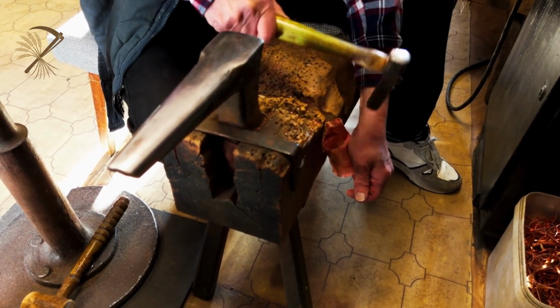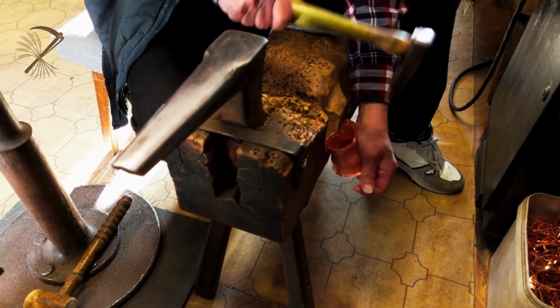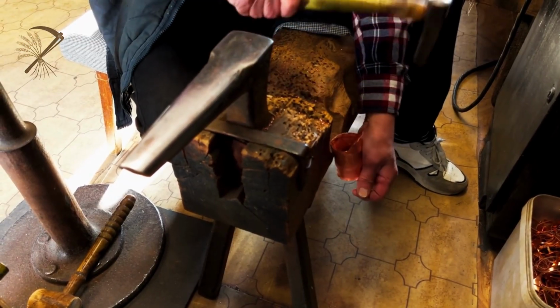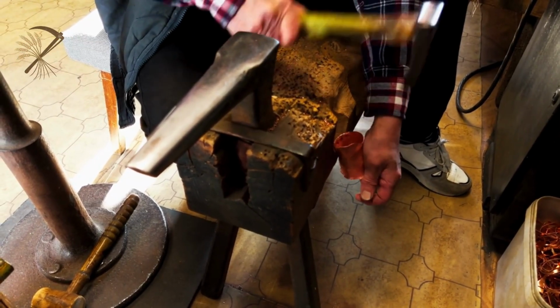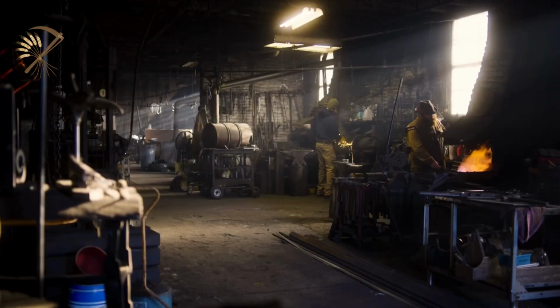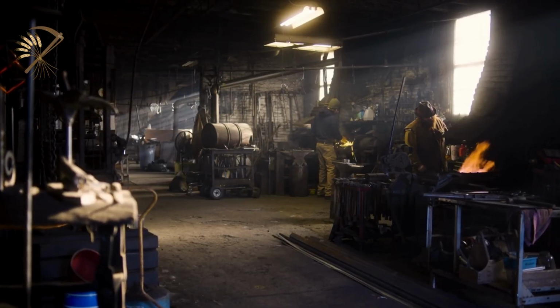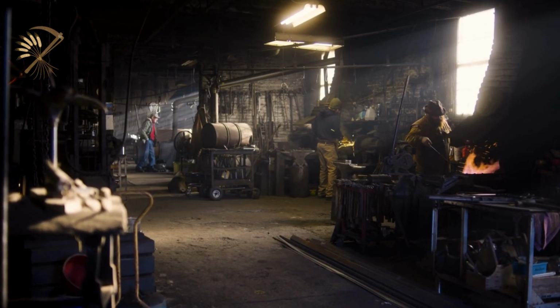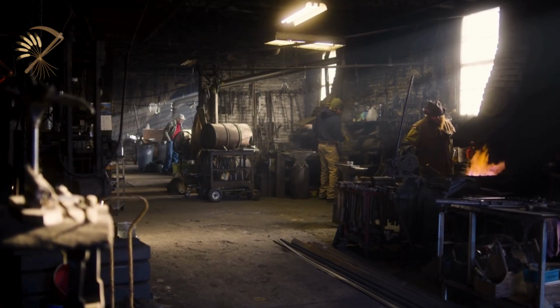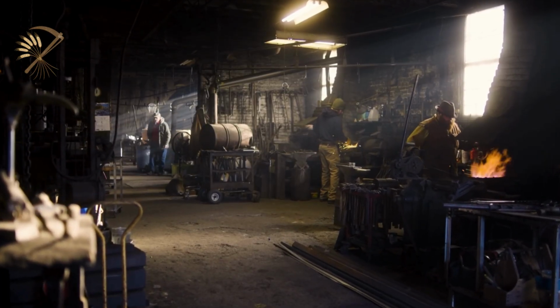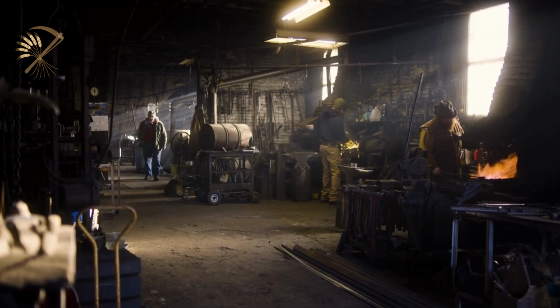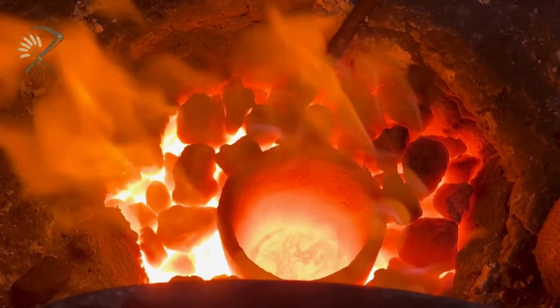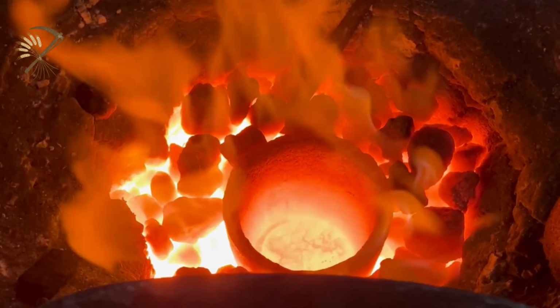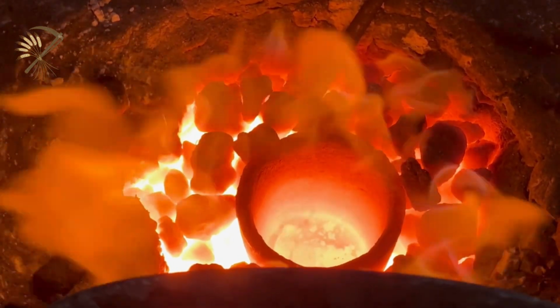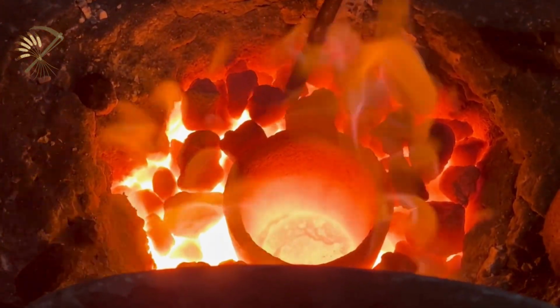This deviation seems minor but significantly affects performance. A hoe ground to 35 instead of 27 degrees requires 30% more force to penetrate soil, tiring the user faster and reducing daily work output substantially. Heat treatment. The heat treatment process, hardening followed by tempering, transforms properly shaped high-carbon steel into a functional cutting tool with the hardness to hold an edge and the toughness to resist breaking under impact.